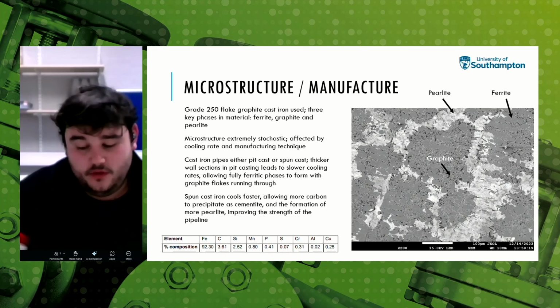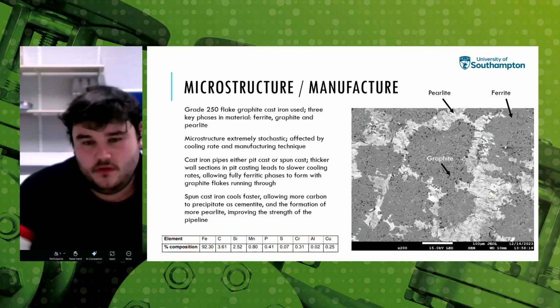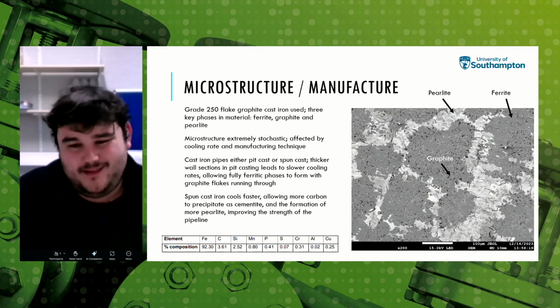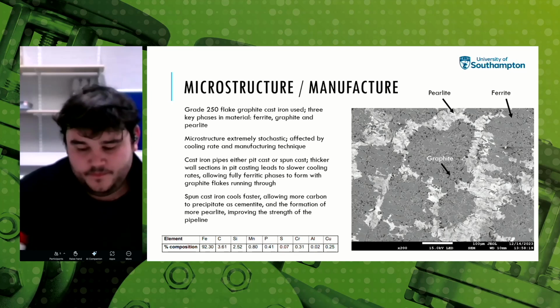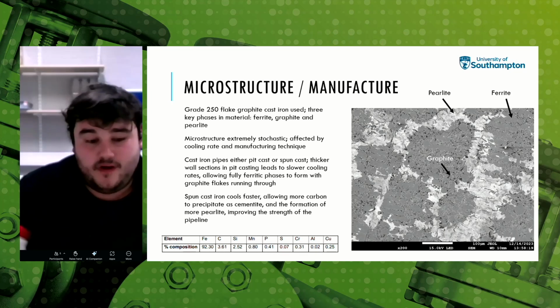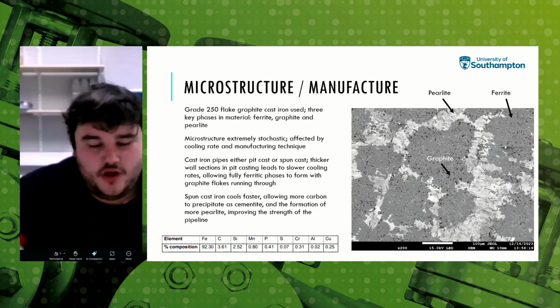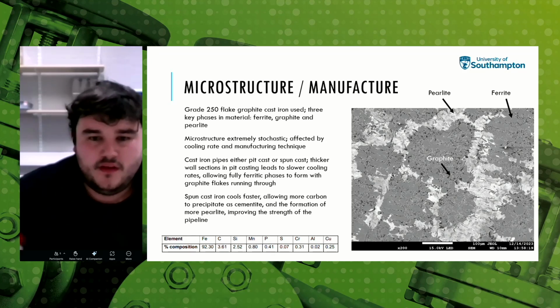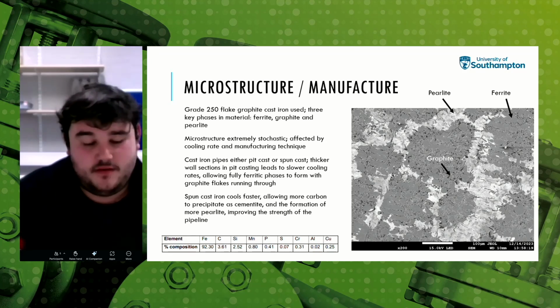And a large variation in all the phases, particularly the graphite flakes. This is a crucial point, as they can be considered structurally as voids. They effectively provide a stress concentration throughout the material that encourages the initiation and propagation of cracks through the pipeline, and therefore is a huge factor in studying its strength.